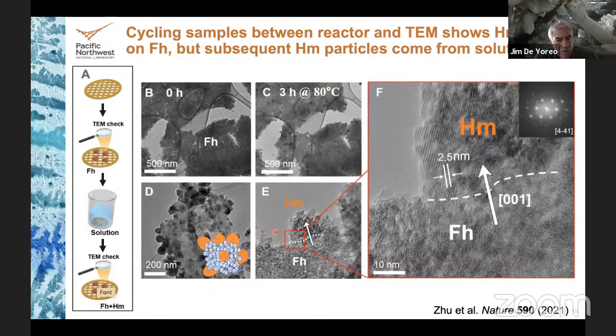But once the hematite starts to form, the spindles grow out from the ferrihydrite into the surrounding ferrihydrite-free solution. So you can see these are half spindles now. All of them are half spindles. They point out into solution. Here's the boundary. And that means the particles of hematite are adding onto the spindle from out in a solution where there are no particles. That implies that the ferrihydrite is not adding on to the spindles, even though they must start there. But it's being replaced by hematite that forms out here and adds on, but somehow in a deterministic process.